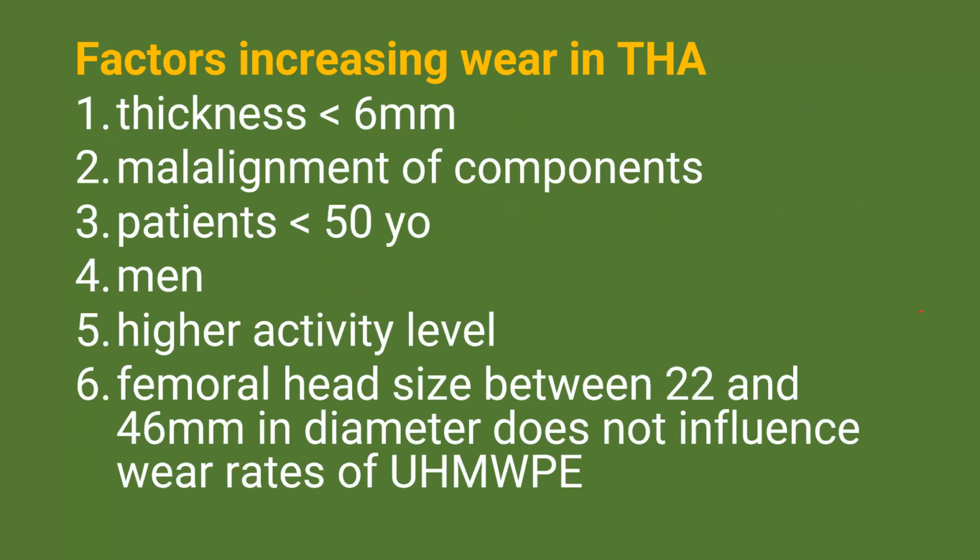The factors increasing the wear in total hip: if you use a cup with polyethylene less than 6 millimeters, this would wear. Malalignment of the component position. Patients less than 50 years old have a higher incidence. Men have a higher incidence because they walk more. Femoral head size between 22 and 46 millimeters in diameter does not influence wear rates. So please pay attention to this, okay?